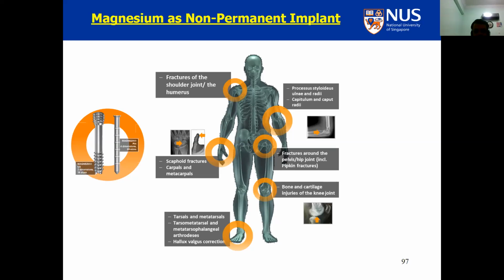If you put magnesium screws or plates to fix the fracture, you put it in and you forget about it, because it is going to get dissolved over time. So you save on the second surgery. That means your 50% of the hospital cost is reduced. And that is the driving force of using magnesium. And that was the message which was in the video.